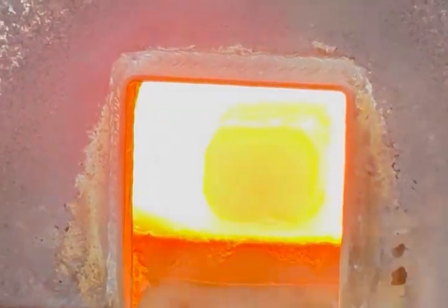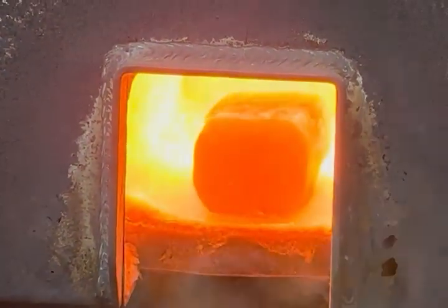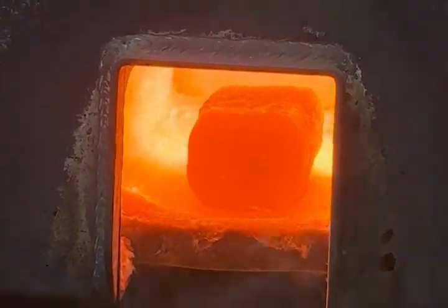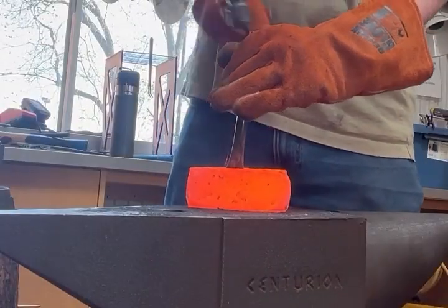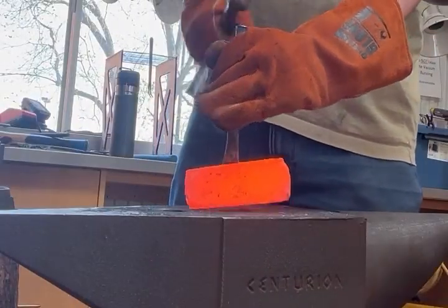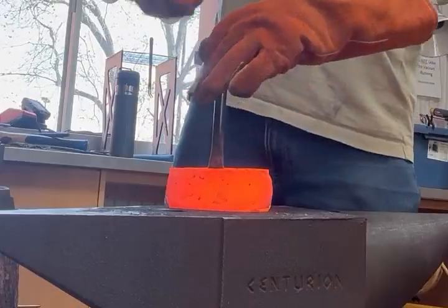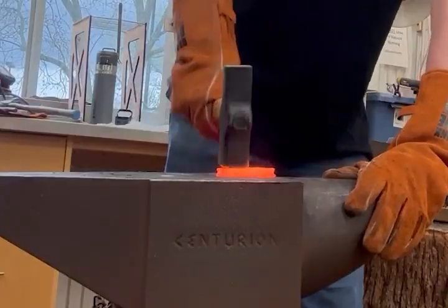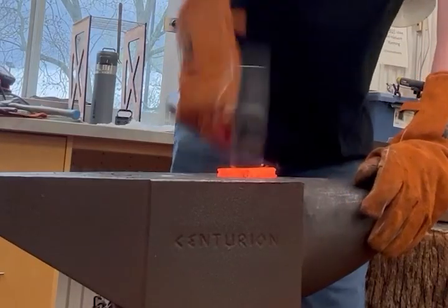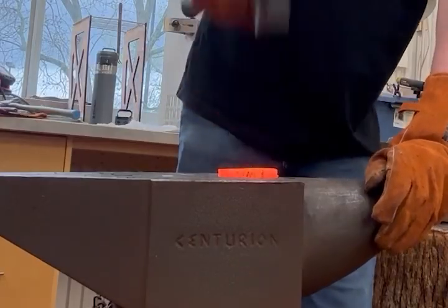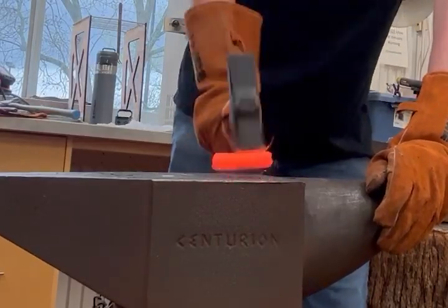I mean, look at this thing. After about 8 hours of work, we ended up with a cross-section of about 1.5 inches by 2.5 inches. We decided for the sake of time it would be much more efficient to simply just punch and drift what we've gotten to so far. And simultaneously, we worked on hammering out the 4340 to a flat bar, and as we started with only a 1-inch diameter steel bar here, this was much more manageable.